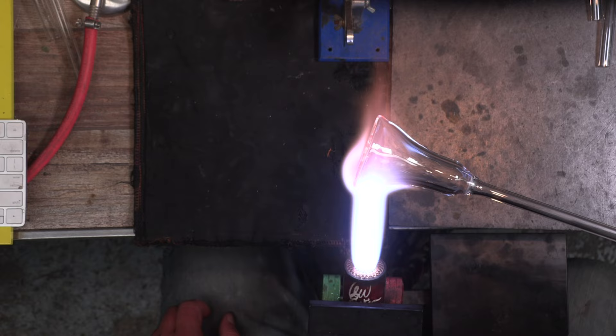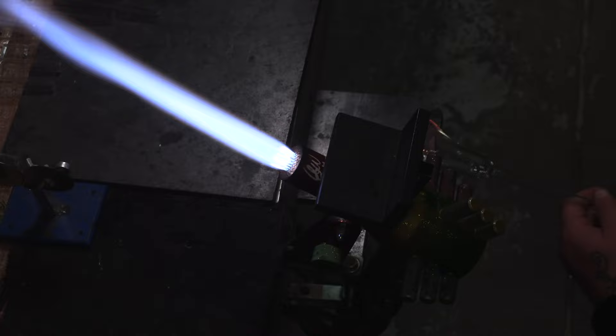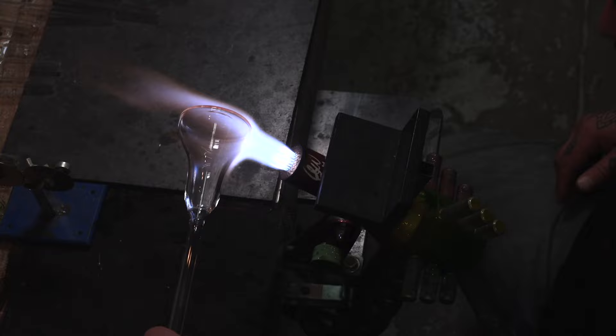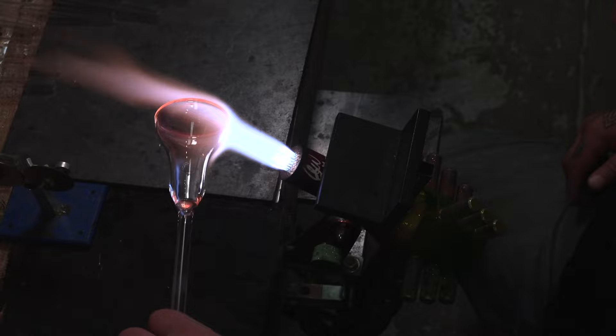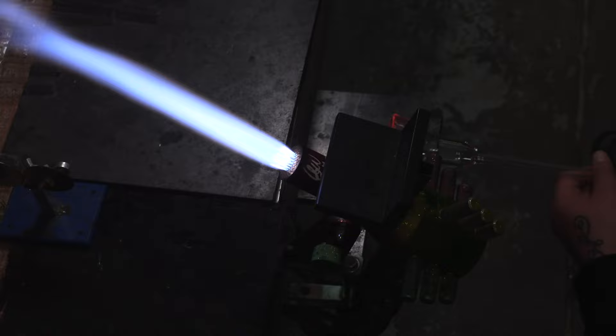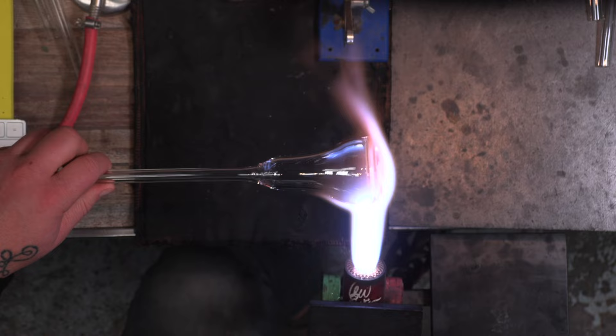I'm going back in on the corner — you can flatten this out, blow it out a little bit. In my case I'm going to hold it down on the marver and create more of a taper shape. I want to make sure to keep it nice and even and warm because if you have a sharp corner you could put stress on the glass. I'm going to blow a little bit and push out that edge to make this more of a triangle shape, but you can make any shape you like.